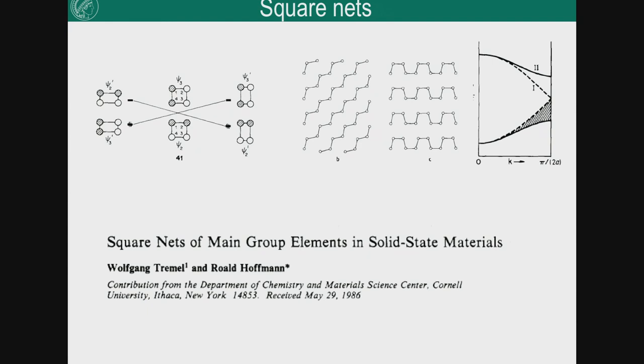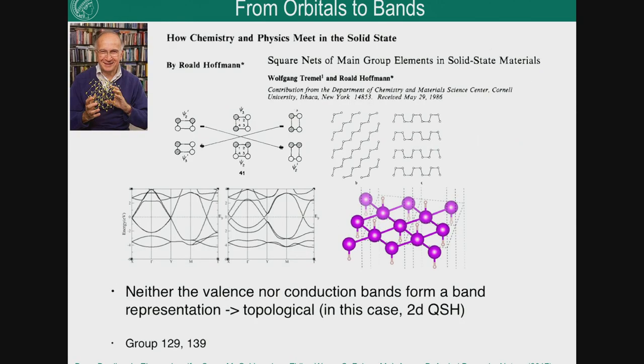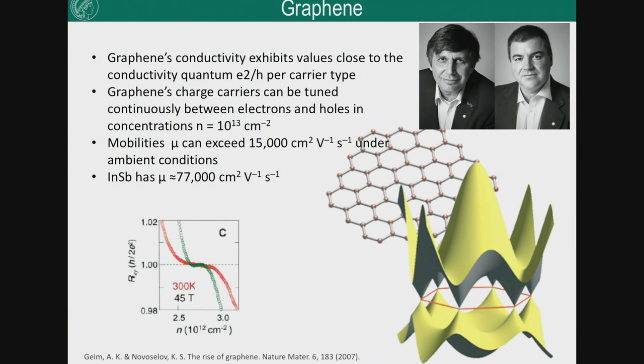But this is not proven. It's simply an intuition, maybe sometime somebody proves it. Because this was written in Andre's paper, that you have this bismuth square net, this distortion doesn't happen, which opens up big band gaps, so you stay with a very nice topological band structure. So in all the space groups 129 and 139, if you have heavy elements, you have these very nice topological materials. One example is, again, the zirconium silicon sulfide, which people are working on because of nodal lines, and many of the bismuth compounds. Many of the compounds in this space group, antimony or tin or lead compounds, are still interesting to investigate. Okay, so then coming back to graphene, and then I make a break because we are nearly through the first part.